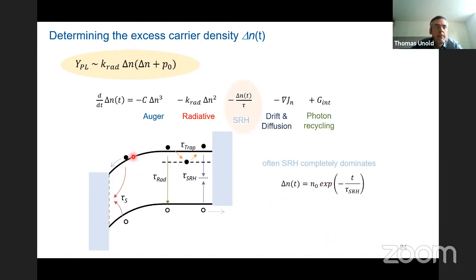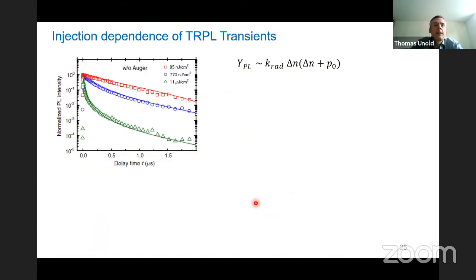So here you can also see what happens. You can have movement of carriers: the electrons go to the N side, the holes to the P side, so you have charge extraction. You can have trapping here, which I will talk about. So there are all kinds of different effects that can happen that sometimes make the TRPL interpretation complicated. But let's start with a still relatively ideal case and look at the injection dependence of the TRPL transients. That's shown here for three different excitation densities. The red one is relatively low, then a higher excitation density and an even higher excitation density. This is the equation describing the photoluminescence.